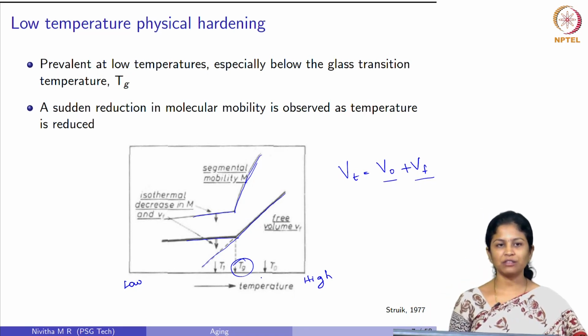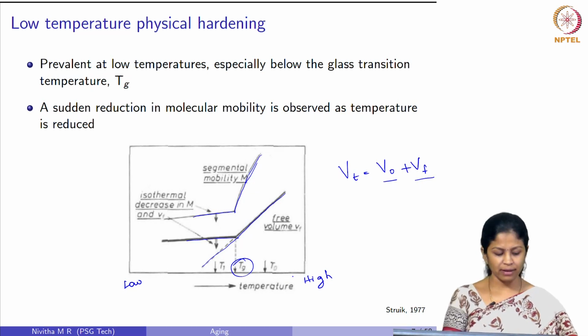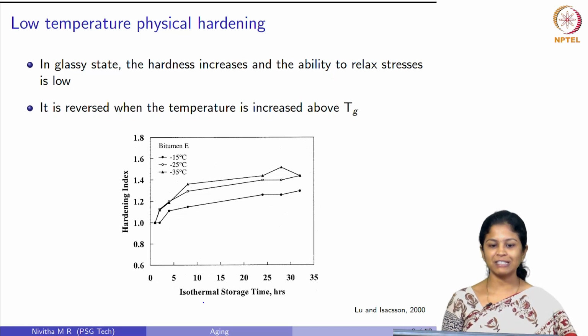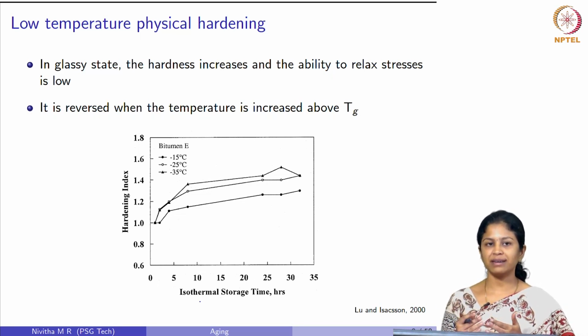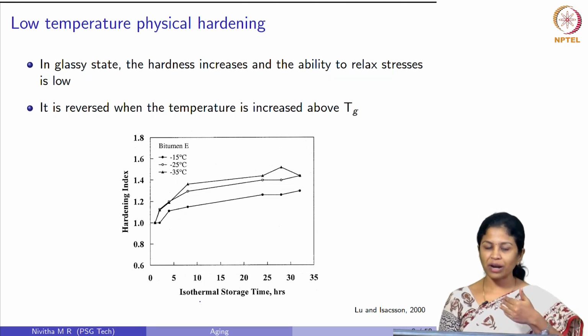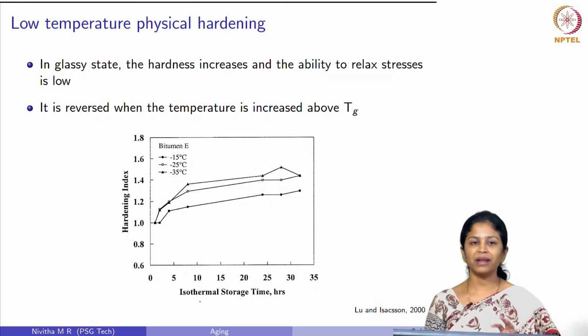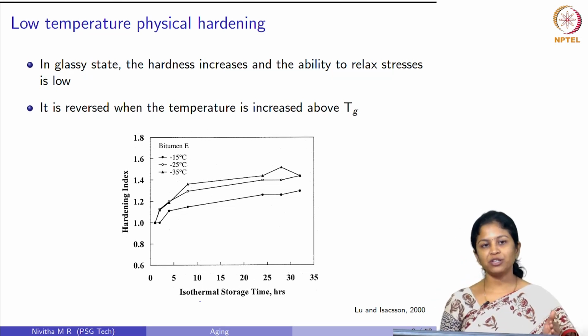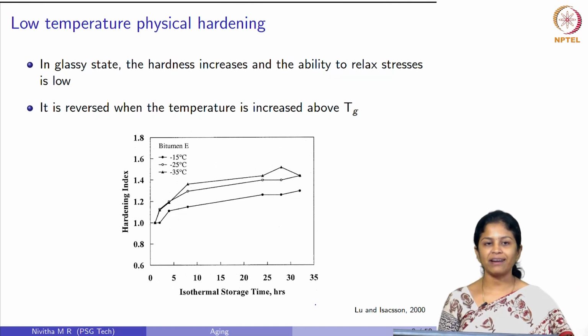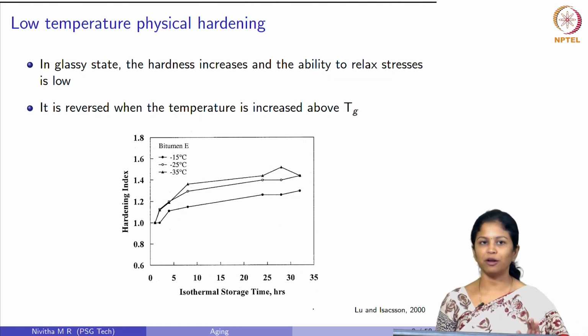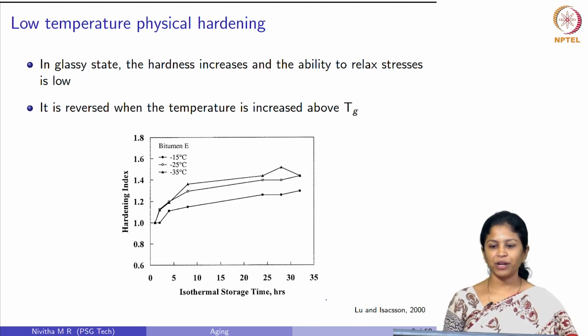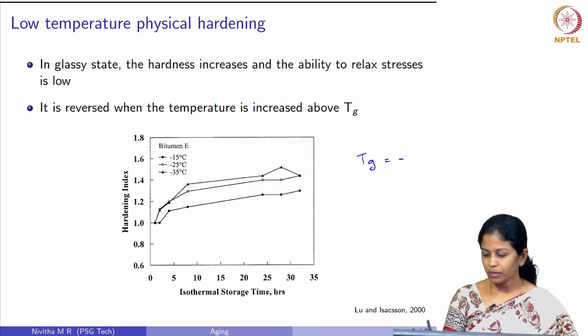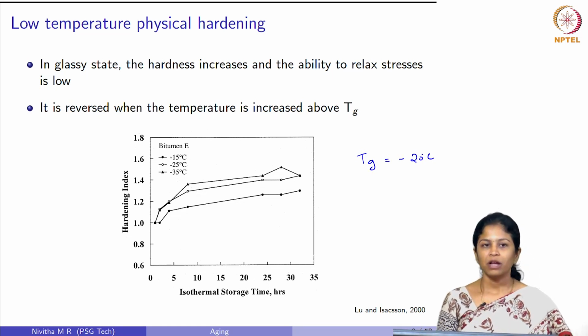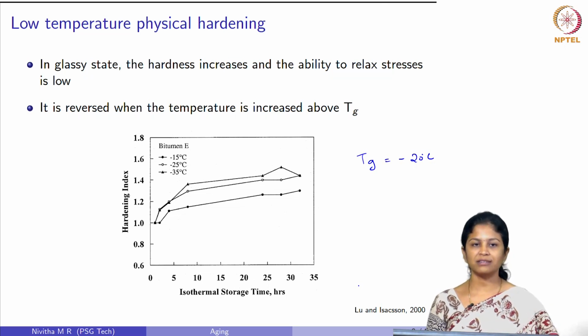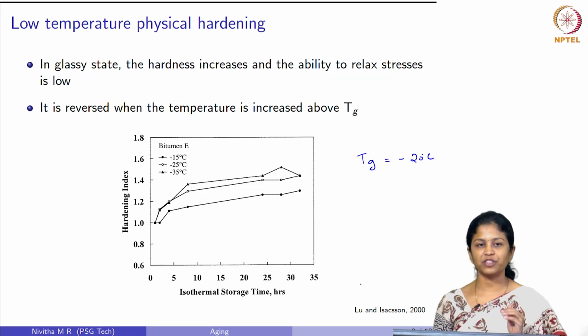Now, what is the consequence of low temperature physical hardening and why are we interested in it in the case of bitumen? In the glassy state, the hardness of bitumen increases substantially and the ability to relax stresses reduces. This is very important for pavements when the temperature falls below the glass transition temperature. This may not be very common in India, but imagine countries like Canada where pavement temperatures can easily reach -30 or -40. Generally, the glass transition temperature of bitumen is roughly about -20 degrees Celsius, a general number. So, when the pavement temperature falls below this glass transition temperature, low temperature physical hardening happens.